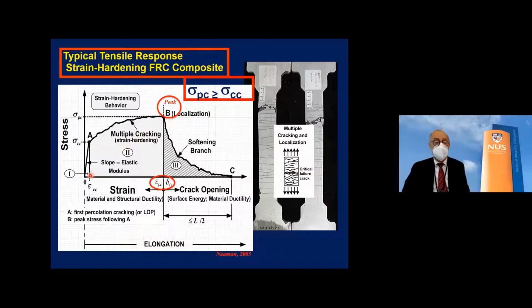It means after initial cracking, which I call percolation cracking, meaning you have a crack going all the way through the specimen. I have a hardening region, that is, the stress increases above the cracking stress. Multiple cracks occur up to a maximum point, called the peak load. At this point, there is what we call localization.